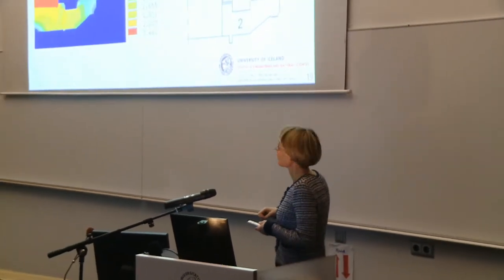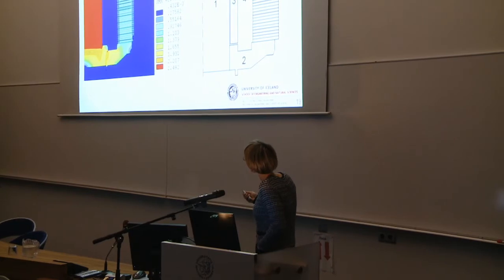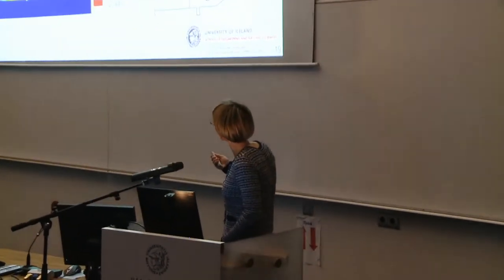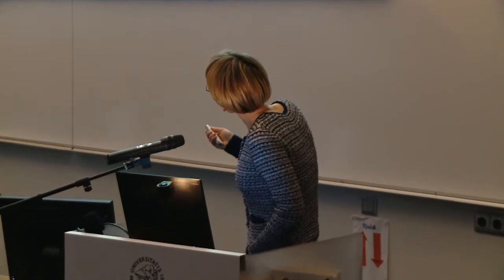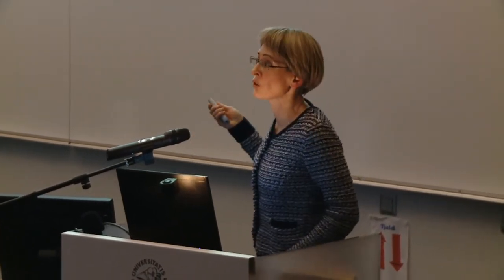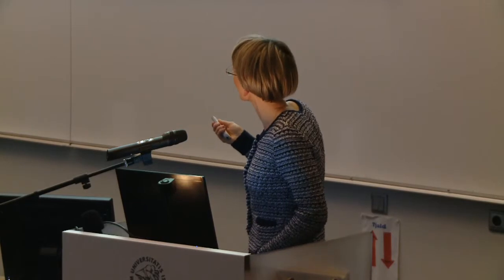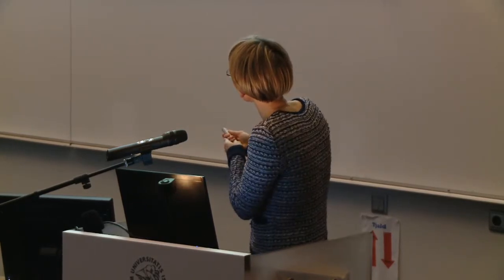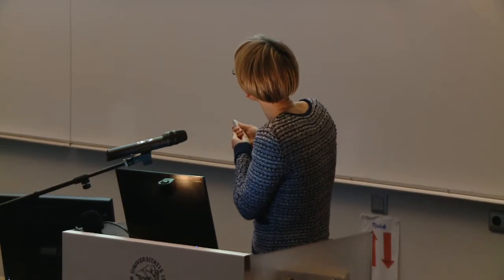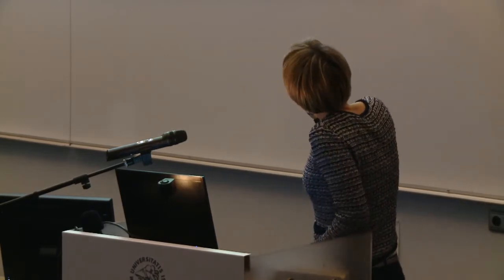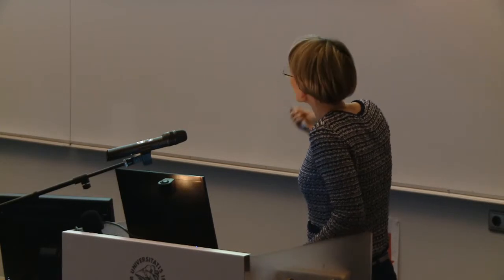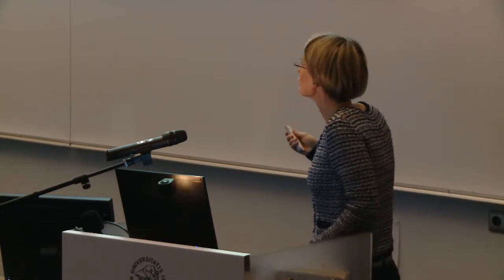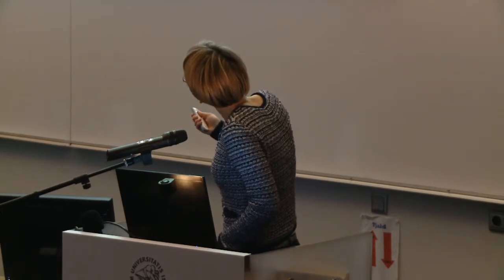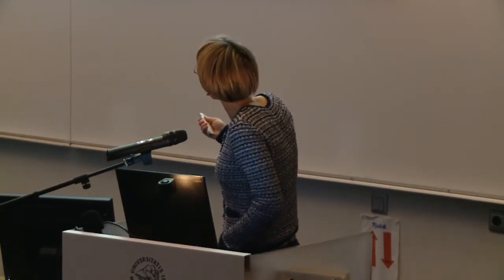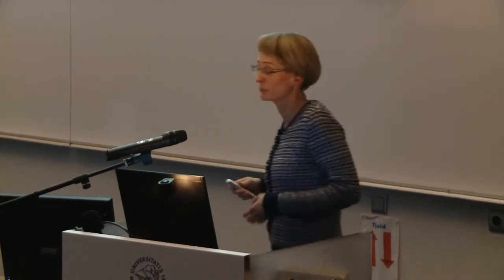How do we determine the magnetic flux density? We can do that by using a finite element analysis. And here you see a 2-dimensional axisymmetric view. Here you have the core, which is made of cobalt iron. The red color here means that the core is saturated. The magnetic flux lines go like this into the fluid. If you look at this one here, this is where you have the fluid and the steel plates. So you want to maximize the value in the fluid. But according to this picture and this design, we are getting an average of about 0.6 Tesla.